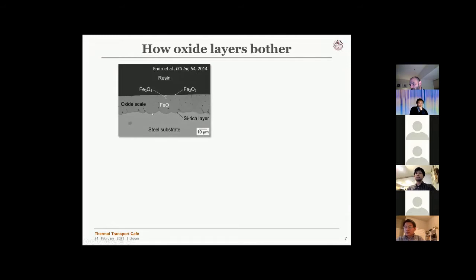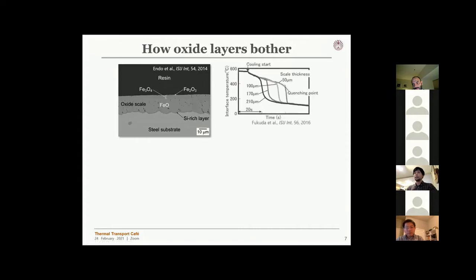Since the steel plate is heated up to several hundred or 1,000 degrees Celsius, you have oxidation on the surface. It has been reported that if you have an oxide layer, you will increase the quenching point.